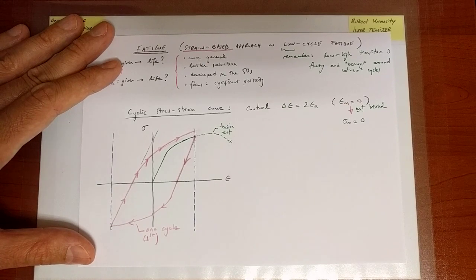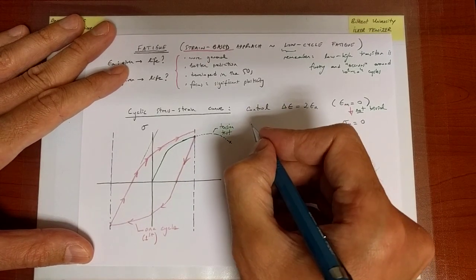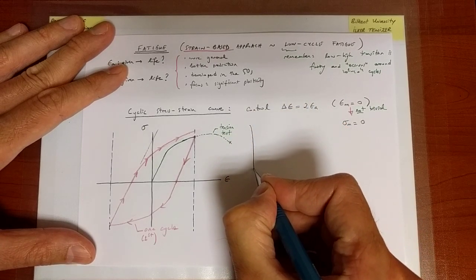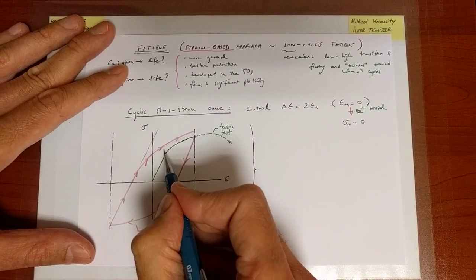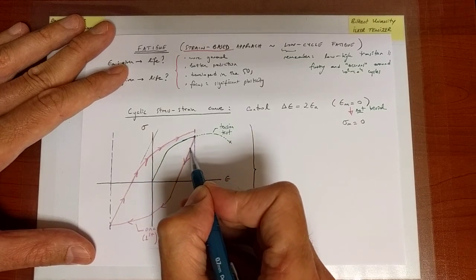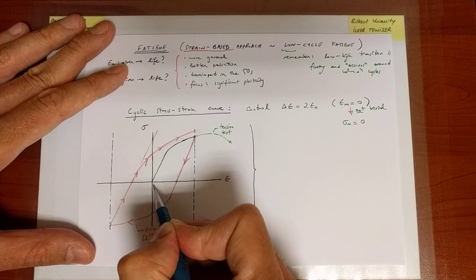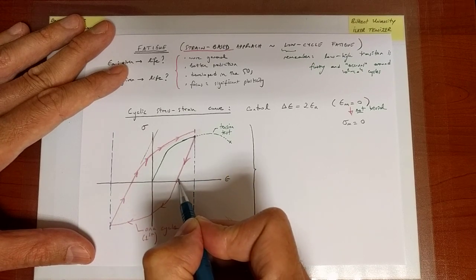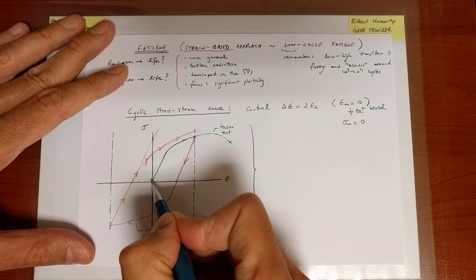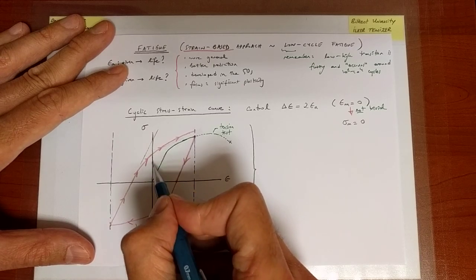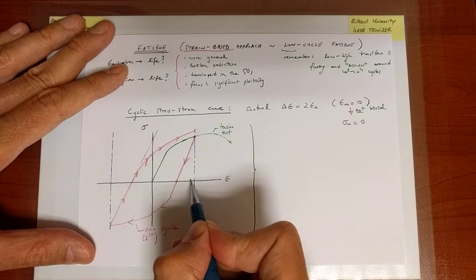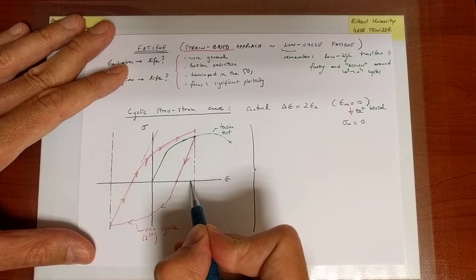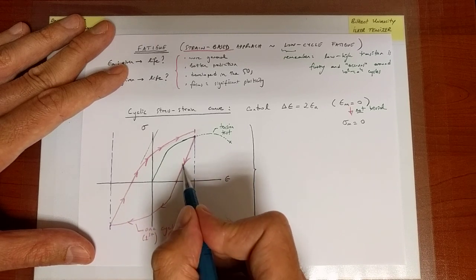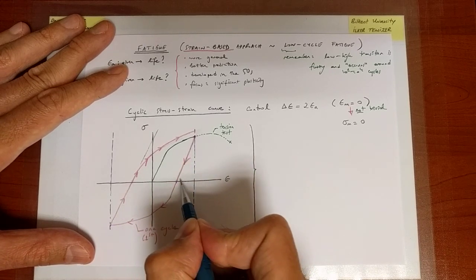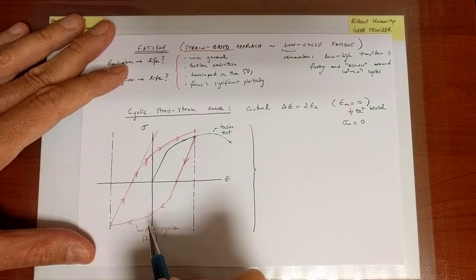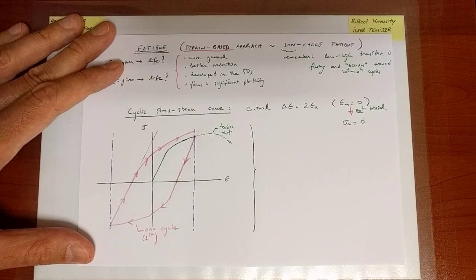Okay, so now here, first of all, notice that we are imposing strains that are so large that significant plasticity occurs. So for instance, in this very first unloading, this is the amount of plastic strain we have. It is significant plastic strain. In fact, remember that this slope is exaggerated. In fact, it's much steeper, and therefore the initial elastic strain as well as this unloading line will be very steep. So at this strain, the amount of plastic strain is very large in reality for real Young's moduli compared to the elastic modulus, which appears large here. In reality, it's not so large. So this is a case where there are significant plastic strains.